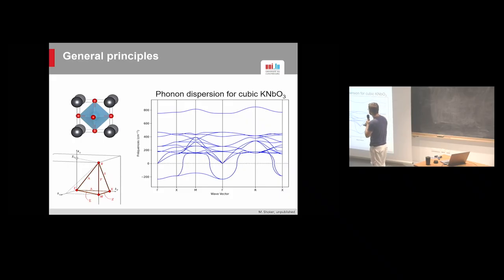And when you do so, you plot this beautiful spaghetti, and you observe in particular the modes that appear as negative frequency. So those are the ones that are unstable. So this dispersion tells you that potassium niobate at 0K, of course, doesn't want to stay cubic, but wants to go to some lower symmetry. Doesn't immediately tell you which one, because we actually have many unstable modes here. Everything that's below 0 is unstable. So you have some at gamma, so long wavelength, but you also have some unstable modes at the zone boundary. So it's not obvious from this picture alone in which phase or in which structure potassium niobate wants to crystallize at 0K. But that's a starting point, and that's also for us experimentalists extremely useful.